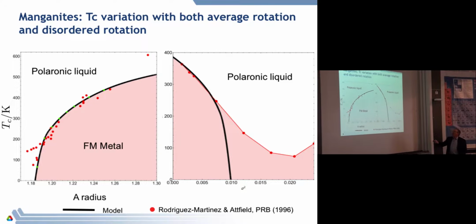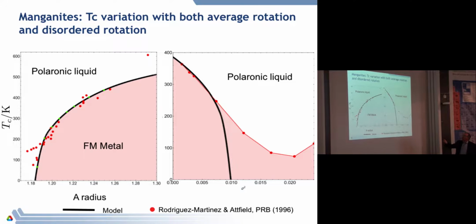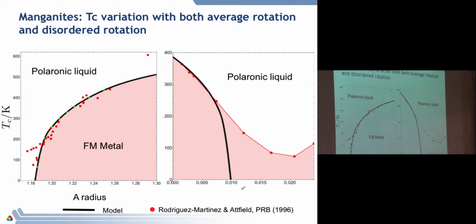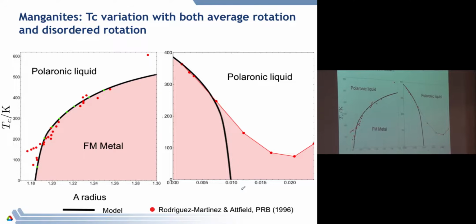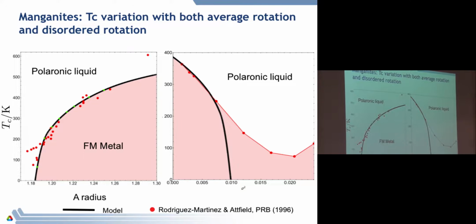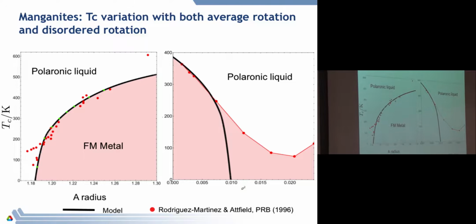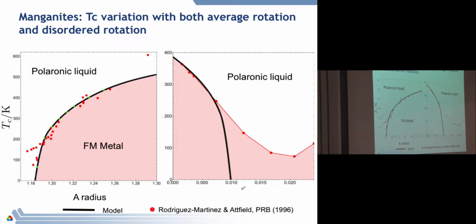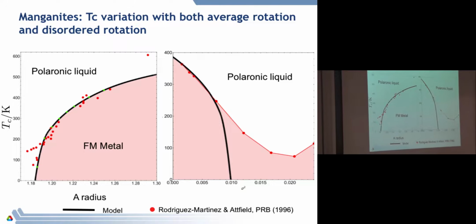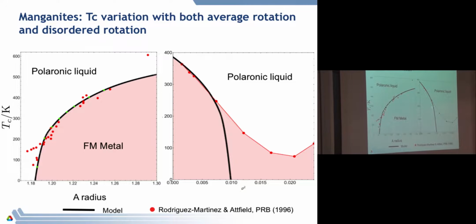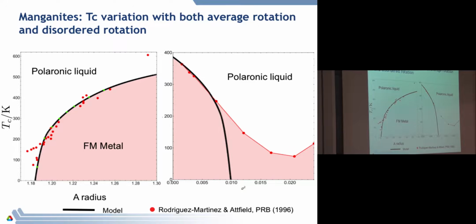And the simple theory for what would happen for the phase transition. So you pick things here to give you a transition between this ferromagnetic state and the non-ferromagnetic state. And then just by varying the radius, with parameters that you essentially know, because they're all associated with elastic degrees of freedom, this goes all of the way down. And by the way, it goes the same way with disorder, and all of these points on here are essentially data. Okay. So you've got very large changes in this, because this phase has a lot more entropy, has a lot more fluctuations built into it than this one.